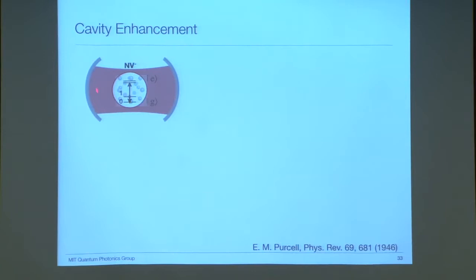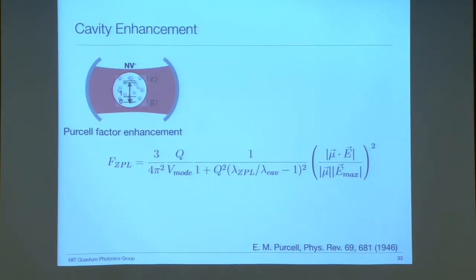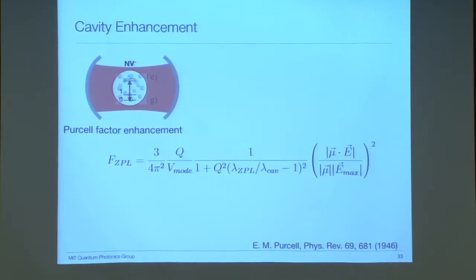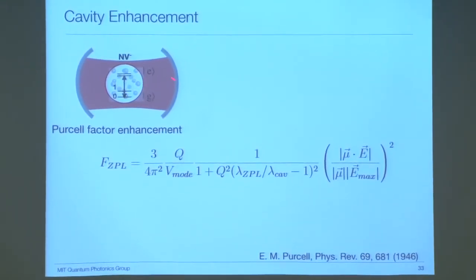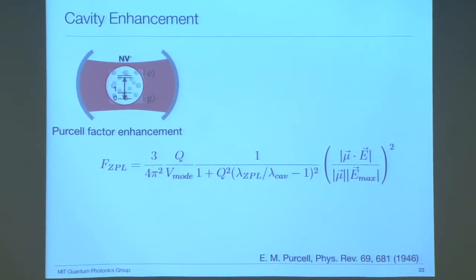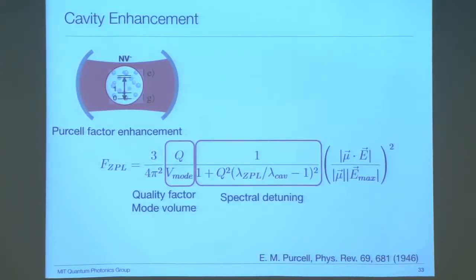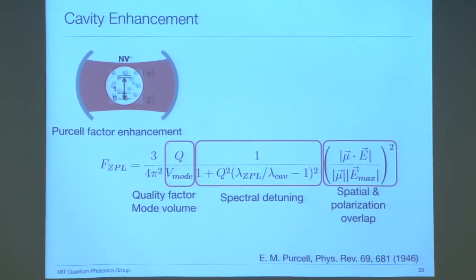When an NV is placed inside of a cavity, its local density of electromagnetic states is increased, and the spontaneous emission rate into the cavity mode is given by this equation. The rate enhancement is essentially proportional to the ratio of quality factor over mode volume. The quality factor quantifies the length of time a photon is trapped inside of a cavity. And this rate enhancement falls off with the spectral detuning of the NV ZPL with respect to the cavity resonance, and also with the spatial offset with respect to the cavity mode maxima.